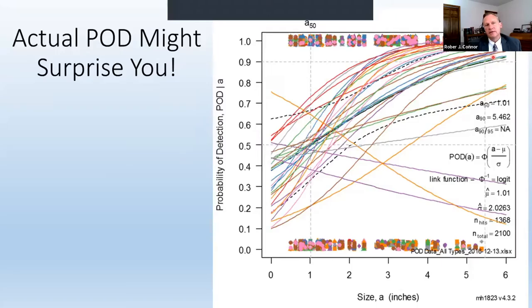Except for these three. For these three individuals, the larger the crack, the less likely they were to find it. Now, that's probably counterintuitive. But what we found, if we look at what we call under data, like years of experience, is that very often we say, well, I'll go get this inspector because they're very experienced. That's not a guarantee of likelihood of finding something because sometimes we get set in our ways.